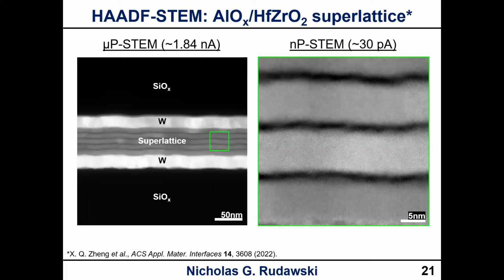8.5 nanometers thick. Okay, so that was very meticulous work that I eventually was able to do, because I had to relocate the area, had to tilt, do all that, but I was able to do it, and I got some really nice images for it. So I was very proud of that. So I wanted to put that in here, right? But anyways, right, that's your hafnium zirconium oxide. That's your alumina. The alumina is only 1.5 nanometers, though.